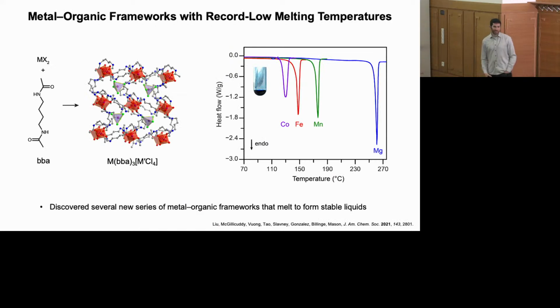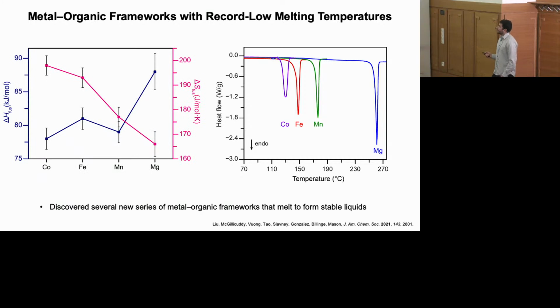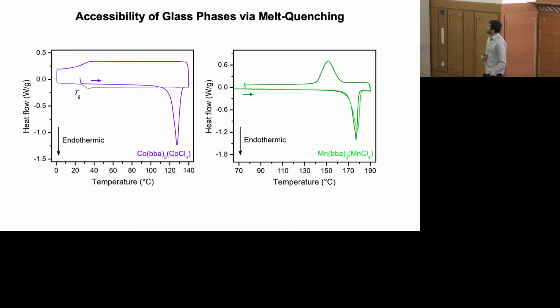And so I'll just give you an example of one class of materials we've developed that really allows us to do this. So this is a class of metal organic frameworks that's composed of a divalent metal cation that's bridged by this bis-acetamide kind of bridging ligand. These form three-dimensional extended frameworks that are cubic in their overall structure. And these undergo melting transitions to form very stable liquids at much lower temperatures than had been possible for any other kinds of extended materials. And we spent a fair bit of time trying to unravel different kinds of thermodynamic relationships and understanding how different structural and chemical changes to these materials influence the enthalpy and entropy changes associated with these melting transitions. But I won't really get into those details.